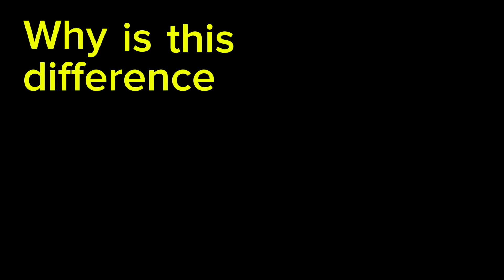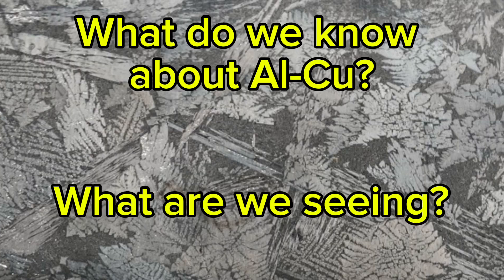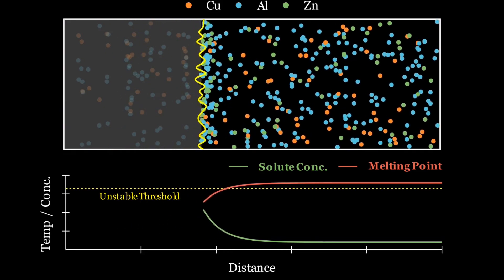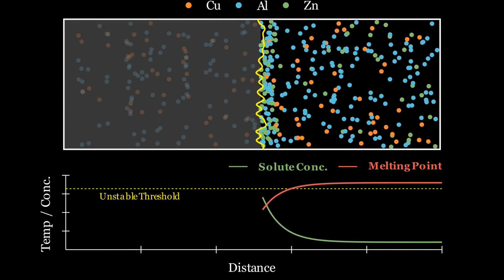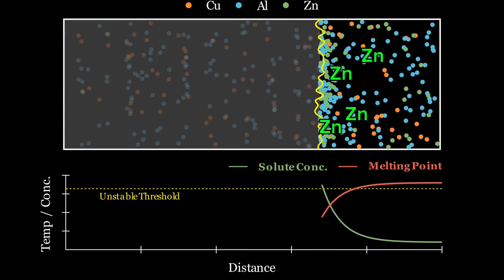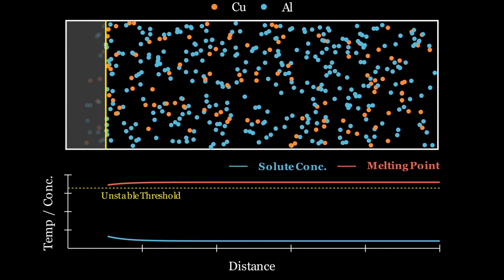So why is this difference present? I'm going to attempt to answer this without a phase diagram, based on what we know about Al-Cu and what we're literally seeing. The answer lies in the zinc — it's mostly allowing for constitutional undercooling. This is the process by which a lower melting point solute is ejected into the surrounding liquid as solid forms from the melt. In our case, that solid is alpha aluminum crystals solidifying first. In our zero percent zinc sample, we obviously have no zinc, but we still have undercooling, just with copper rather than copper and zinc.